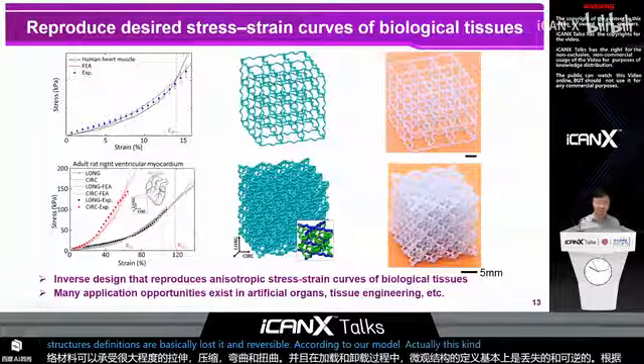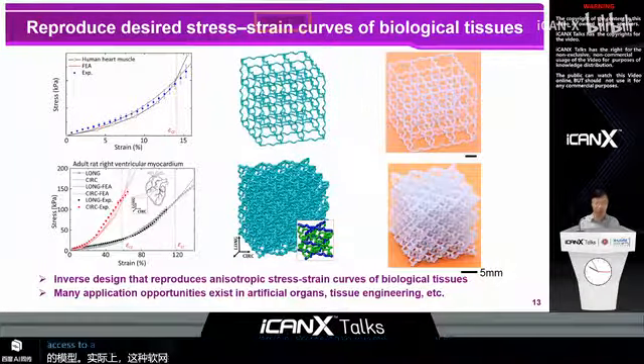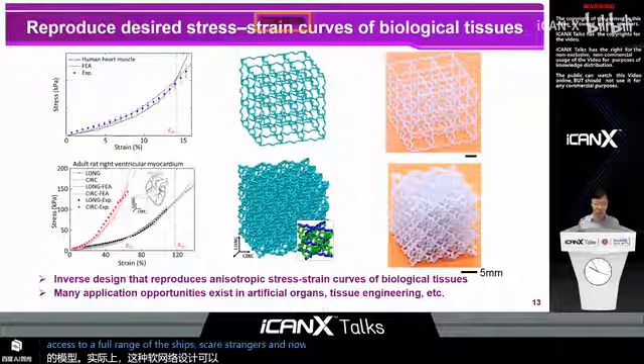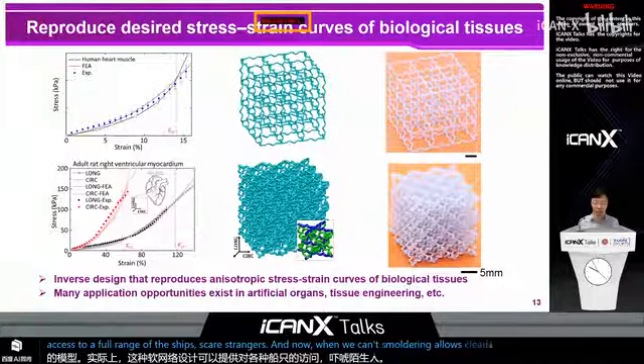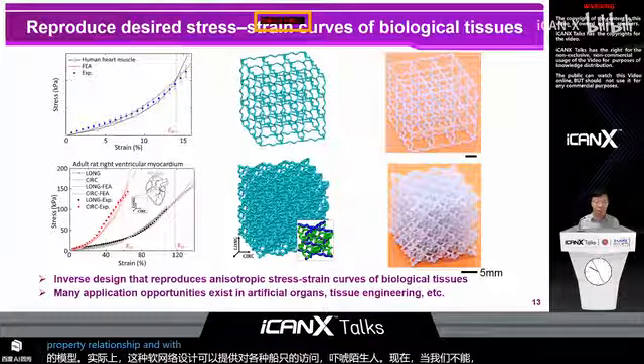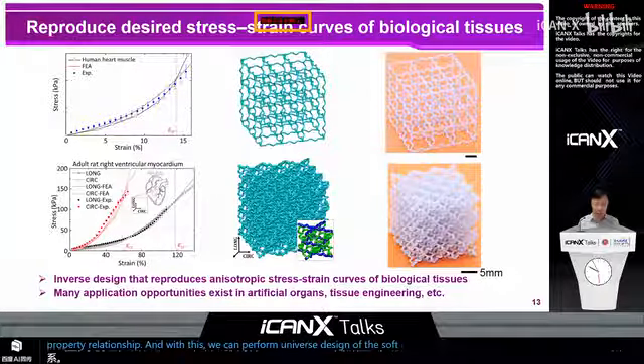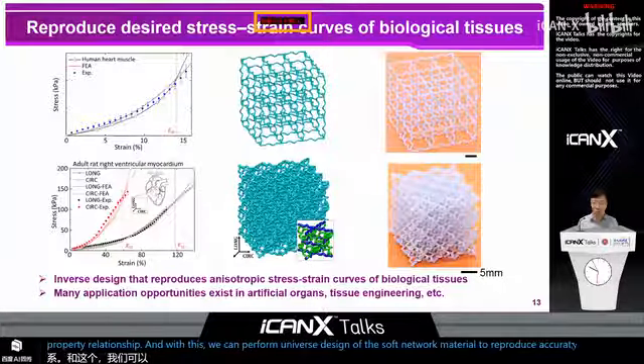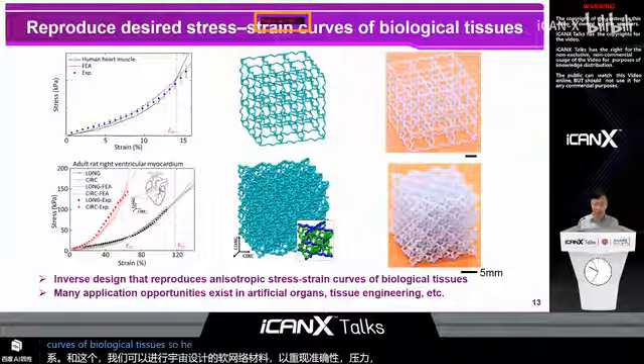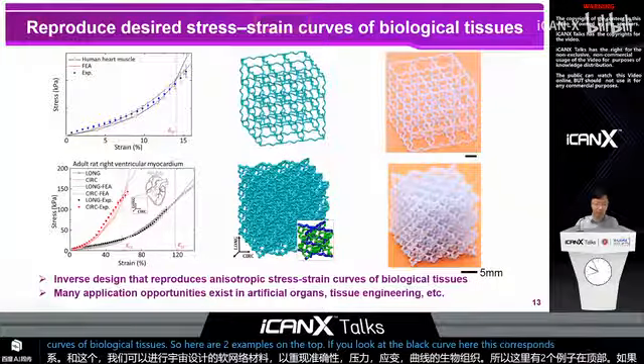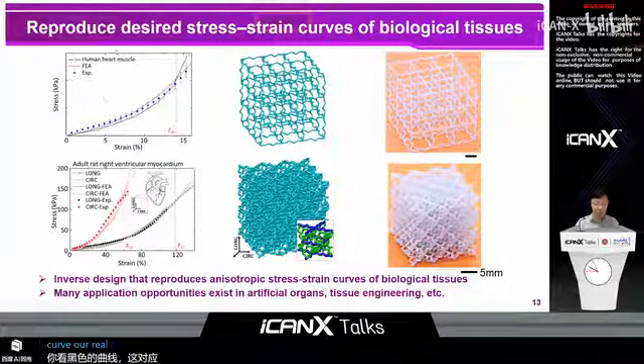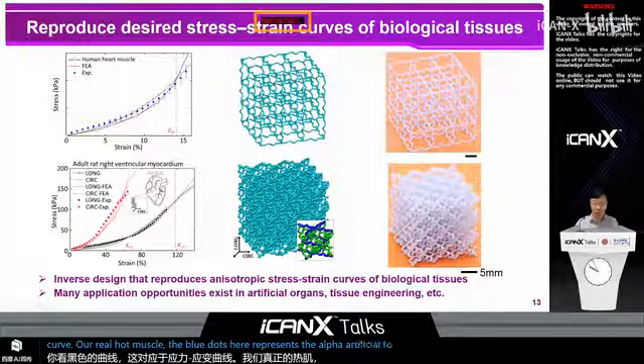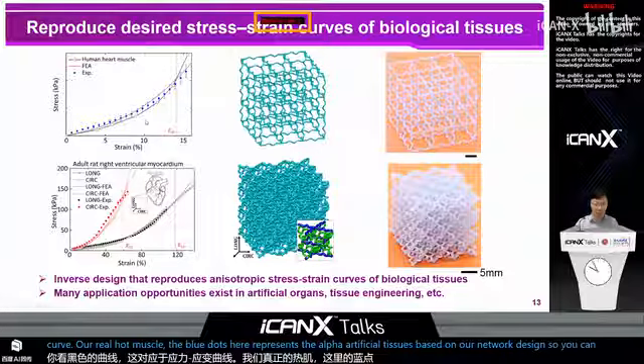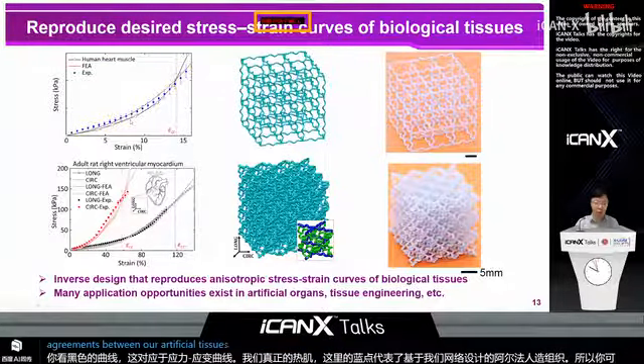Actually, this kind of soft network design can provide access to a broad range of J-shaped stress strain curves, and our mechanics modeling allows us a clear understanding of the structure property relationship. And with this, we can perform inverse design of the soft network material to reproduce accurately the stress strain curves of biological tissues. So here are 2 examples. On the top, if you look at the black curve here, this corresponds to the stress strain curve of a real heart muscle. The blue dots here represent the results of artificial tissues based on our network design. So you can see good agreement between our artificial tissues and the real heart muscle.